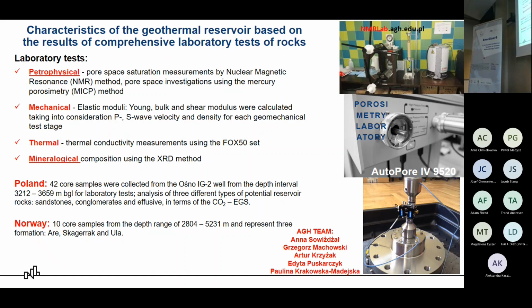These core samples were tested in our laboratory to do a petrophysical characteristic of the geothermal reservoir. We performed petrophysical, mechanical, thermal, and mineralogical tests. In case of petrophysical analysis, we measured pore space saturation by the nuclear magnetic resonance method, as well as pore space investigation using the mercury porosimetry method. In case of mechanical parameters, we tested parameters like elastic moduli, Young, bulk, and shear moduli. And in case of thermal measurements, thermal conductivity was the parameter in which we were interested. We also did mineralogical analysis using the XRD method.